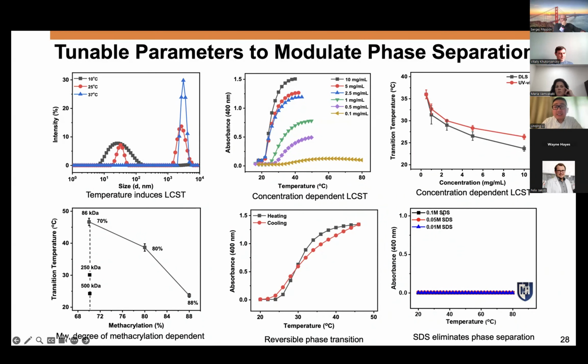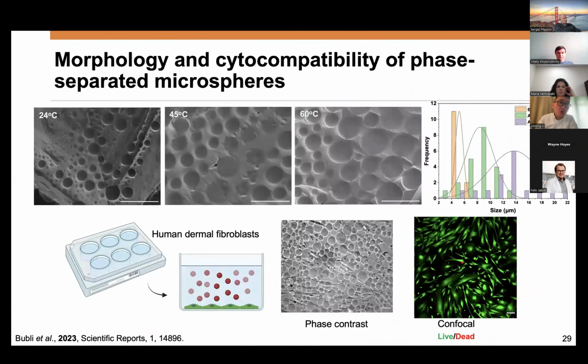Lastly, we're trying to understand the mechanism of this phase separation in our system. We know that when you increase the modification, you go methodically from hydrophilic to hydrophobic residues on the molecule. When we added the surfactant SDS to the system, even at 0.01 molar concentration, you see no phase separation induced at any of the temperatures we heated. This indicates that the SDS successfully dissociated the hydrophobic interactions. So we hypothesize that during phase separation at high temperature, there is a higher possibility of collision of the hydrophobic residues, the methacrylates, which is the driving force for the phase separation. Then we're looking at the morphology.